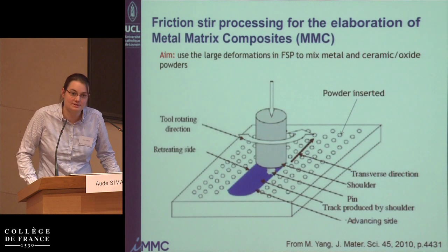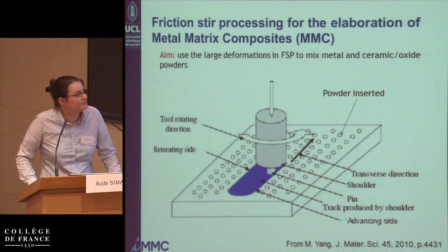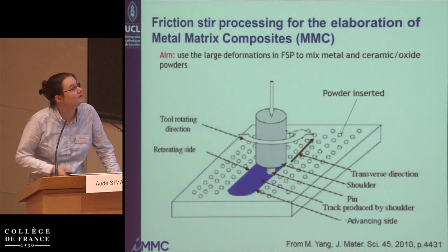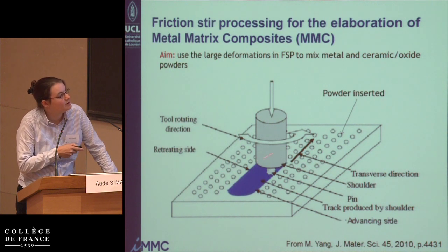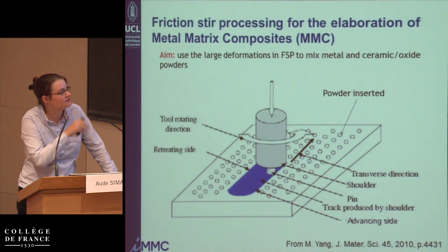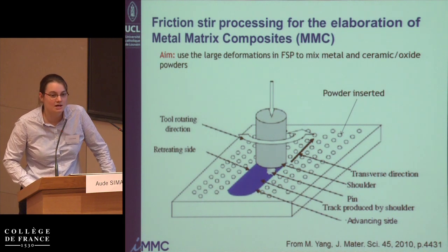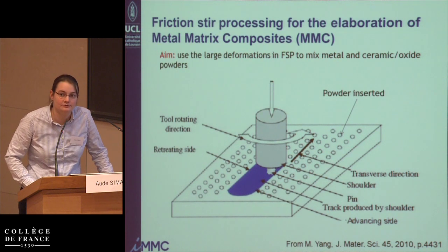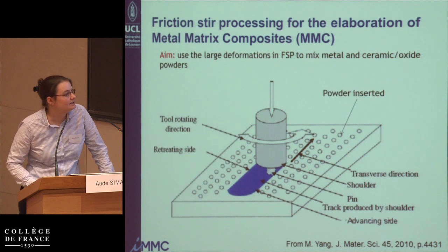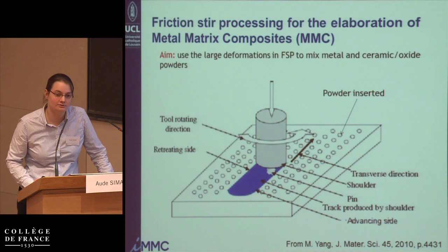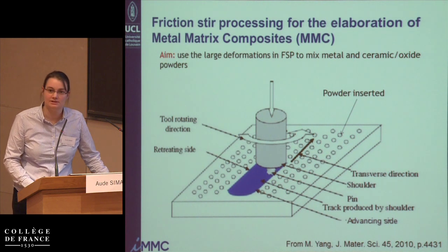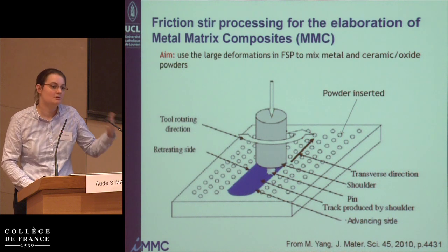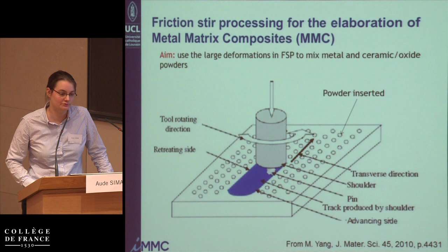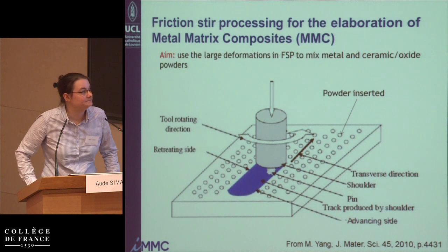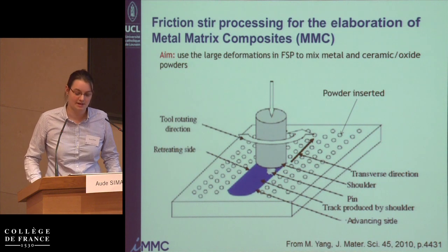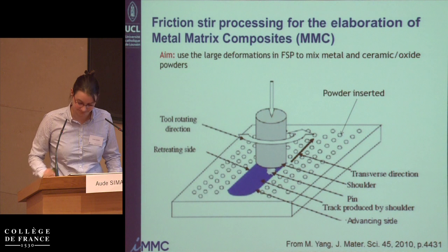Now we want to make some metal matrix composite. So let's go one step further and put some powder of the reinforcing material inside the little holes here, and so you can make grooves, holes, or any kind of shape to insert some powder, and then you take your tool, you go inside the material, and you mix all that. So you use the large plastic deformation at relatively high temperature, but below the melting temperature of the material, to actually mix your powder into the metal. And so you end up with a metal matrix composite.